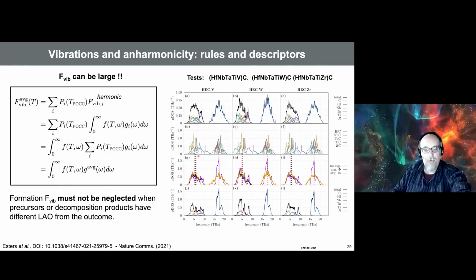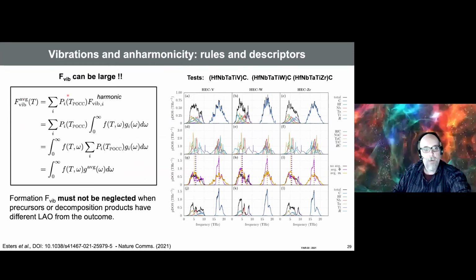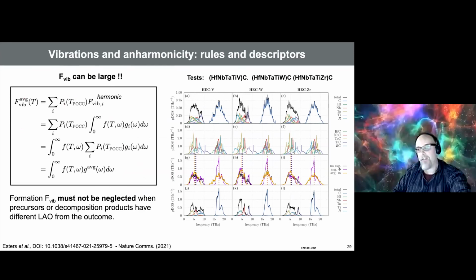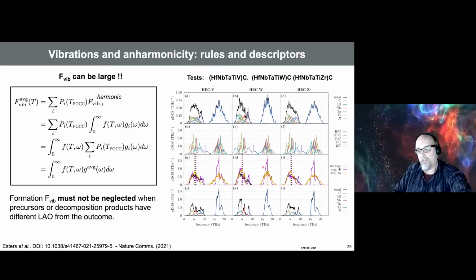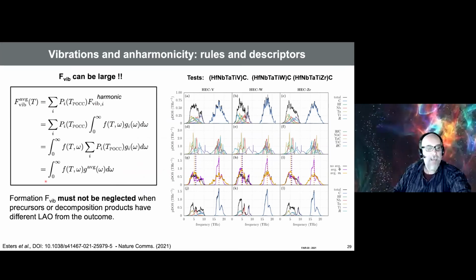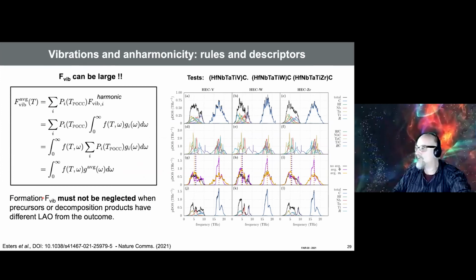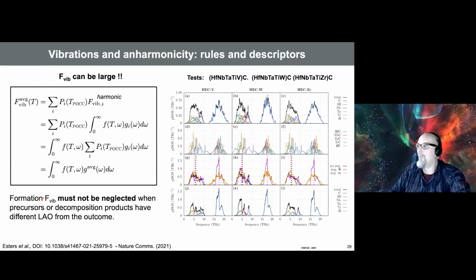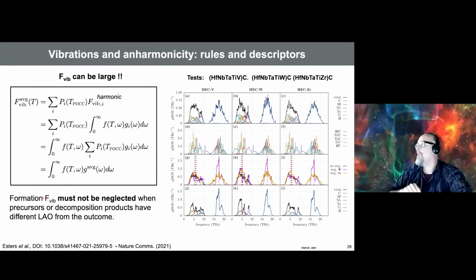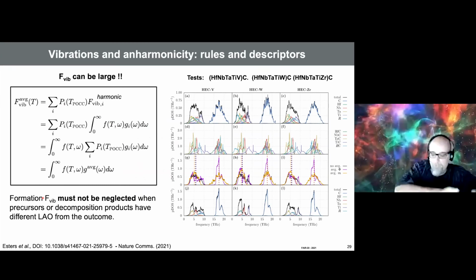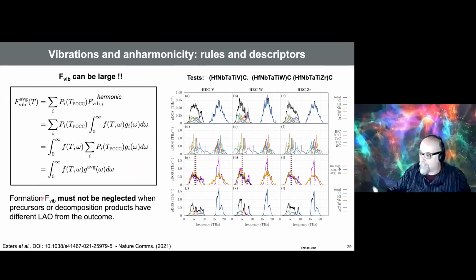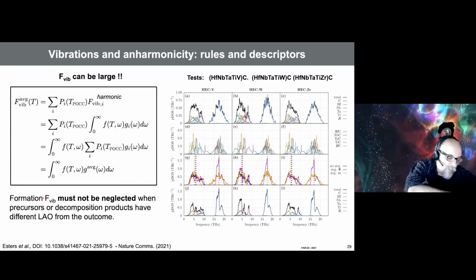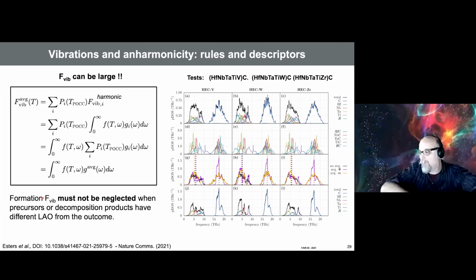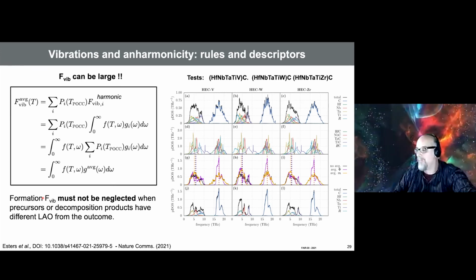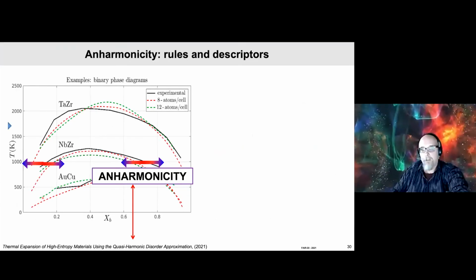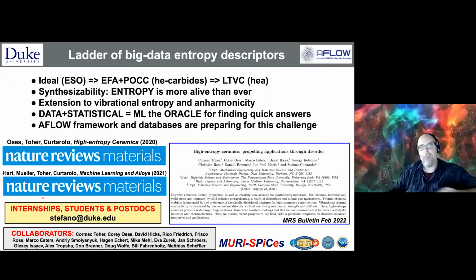So this is the article, and this is the solution. So we did the proof of concept with the harmonic approximation. We are able to calculate all the density of states, and we are able to show that the formation enthalpy contribution of vibrations can be neglected if the precursors have the same symmetry. If you're mixing cubes with cubes and you get cubes, neglect the vibrations. If you're mixing cubes with hexagons and you get cubes, then you need to take care of vibrations. And this is the message of this paper. Then we also did anharmonic, but let me end.